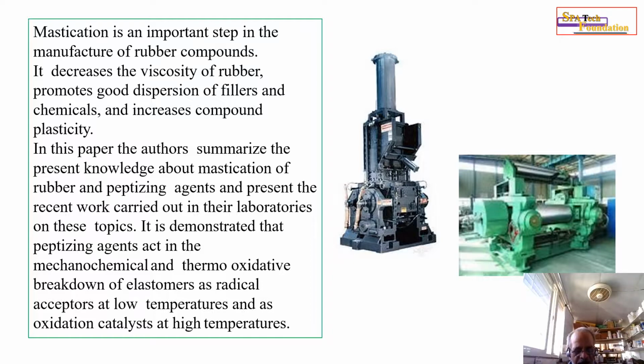It is demonstrated that peptizing agents act in the mechanochemical and thermo-oxidative breakdown of elastomers as radical acceptors at low temperature and as oxidation catalysts at high temperature. You can see the photographs of an internal mixer and a two-roll open mixing mill.